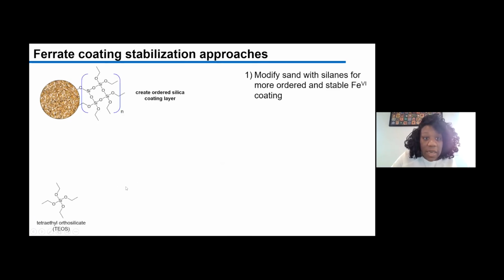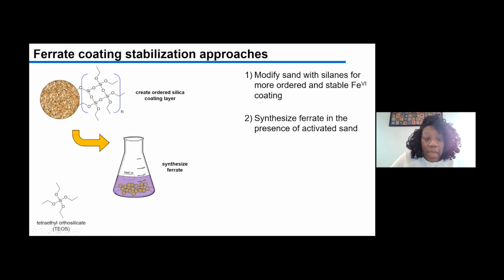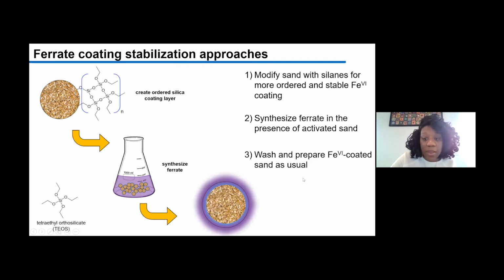We start with the sand, and we found that just adding sand to a ferrate solution results in pretty weak binding. So what we did was we added a chemical modifier, this tetraethyl orthosilicate, to the sand surface, which, as you can see, just has a bunch of silica bonds here. And this TEOS also helps to create almost like a silane polymer around the sand surface. And that helps to have a greater binding affinity for when we add this modified sand to ferrate that we're synthesizing in the lab. So we mix these two together, and then we wash and prepare the ferrate-coated sand for subsequent analyses.